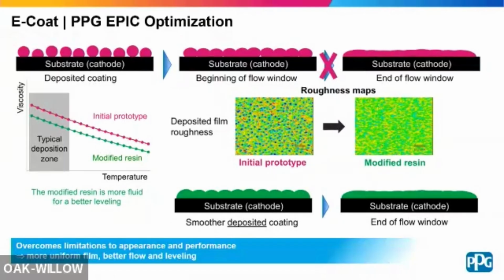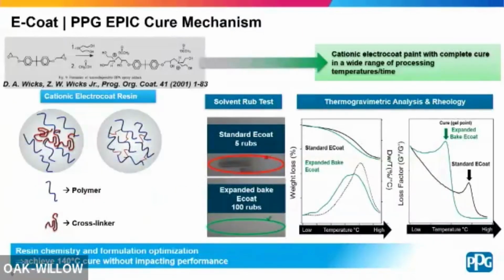And here you can see a traditional or an initial prototype of where we kind of started with this, and you're looking at the roughness, where we didn't achieve the flow we wanted before it started to cross-link. So we had to make some changes, and you can see here with our modified resin, you're able to do that. So now you have a flowable material that'll cure when you want it to cure, and you'll be able to get the performance that you want. So what comes next? Your curing mechanism.